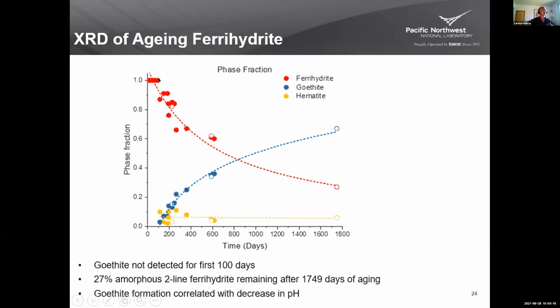So over the first 100 days, it's dominated by ferrihydrite, and then the conversion to goethite starts to occur, and then it occurs monotonically over these relatively long timescales with the ingrowth of goethite and this relatively constant hematite component. And it just shows that although ferrihydrite isn't the thermodynamically stable phase, because of the kinetics, we are seeing ferrihydrite present in these systems at relatively long timescales.